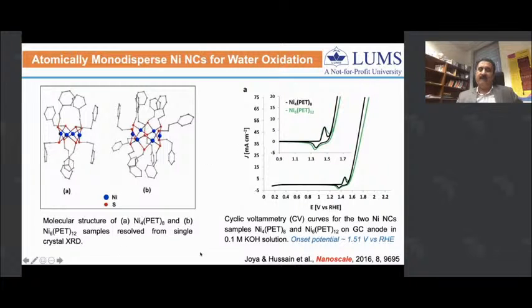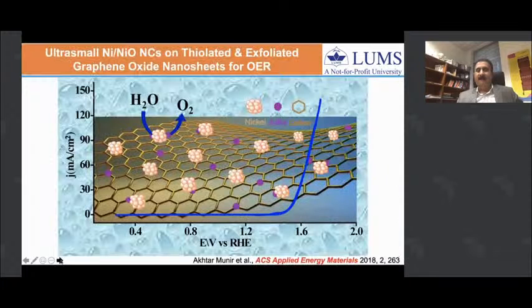So to make this process more economical and practically feasible, you need to have these clusters on various supports. For this purpose, what we did recently is functionalize graphene oxide with thiol, making use of epoxide groups on graphene oxide, then converting that into thiol groups through a series of chemical reactions. Then we generated these nickel nanoclusters on this support.